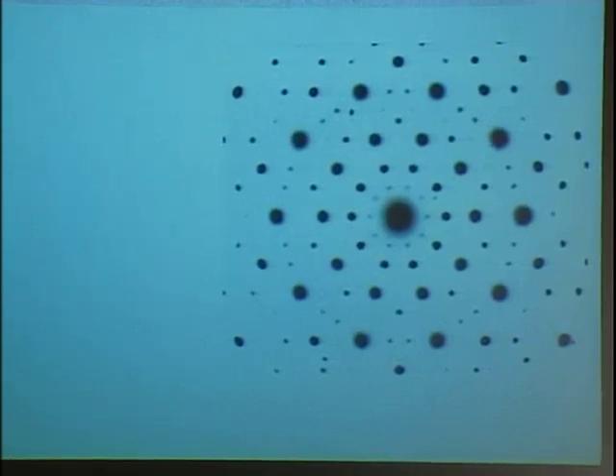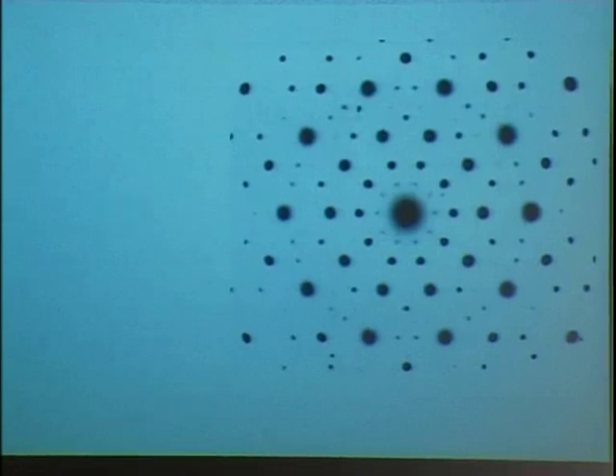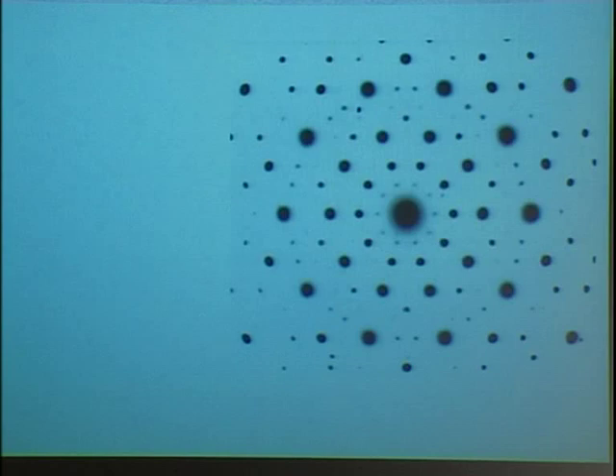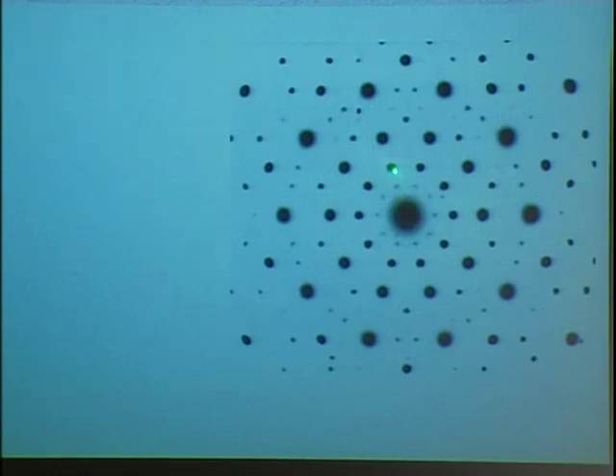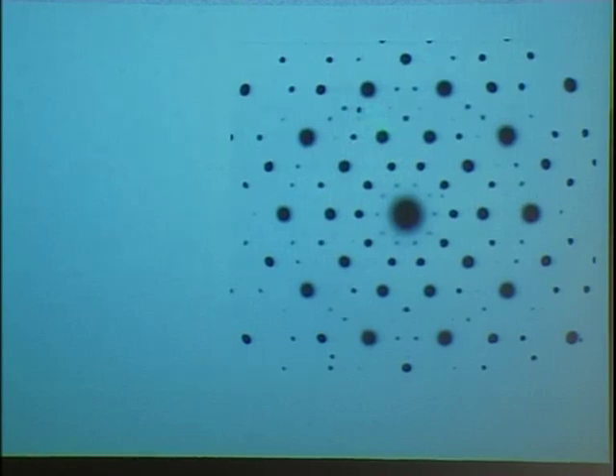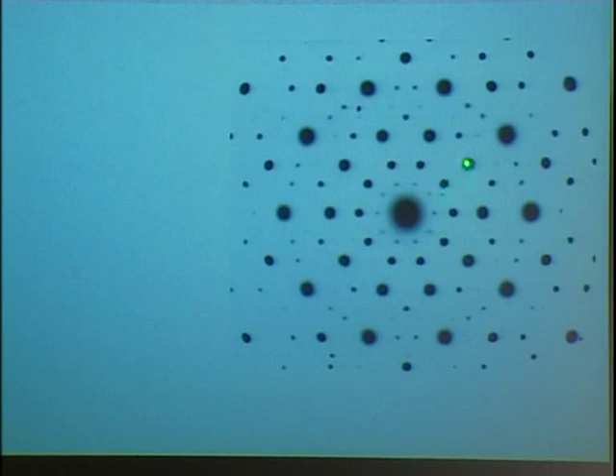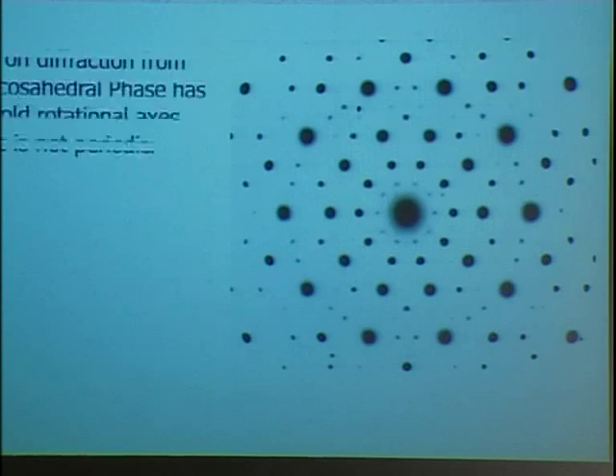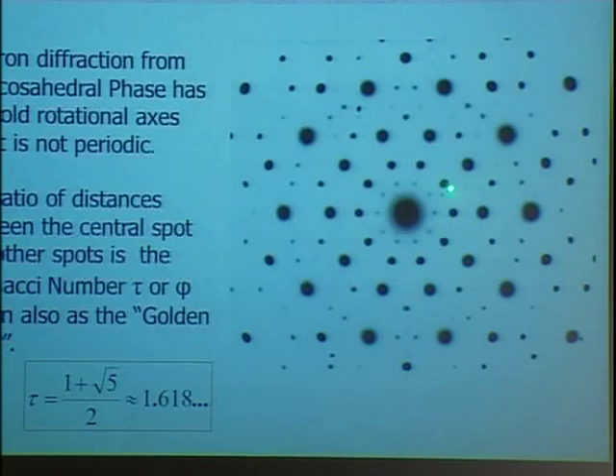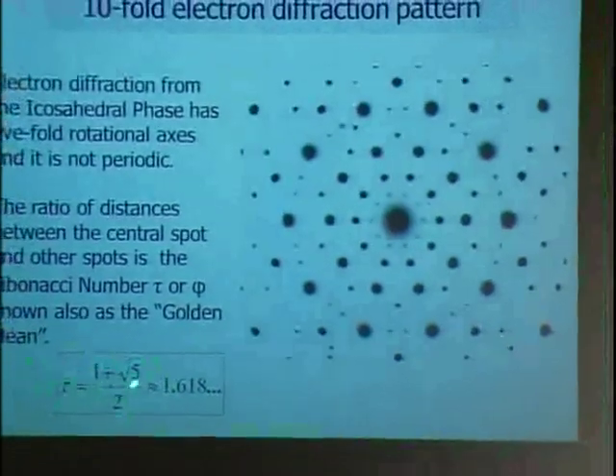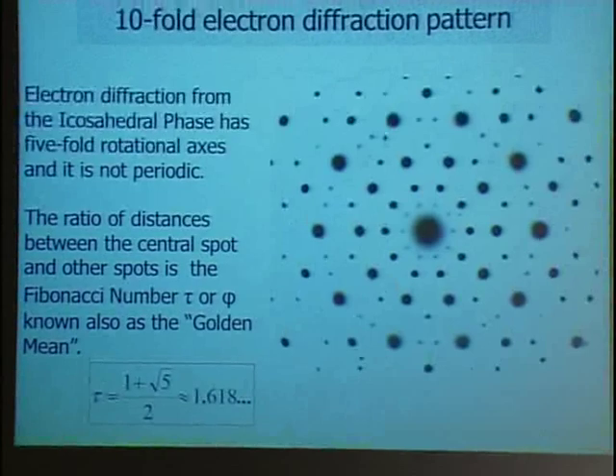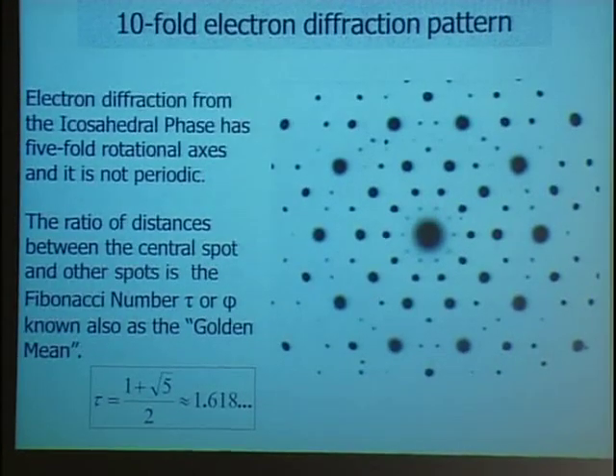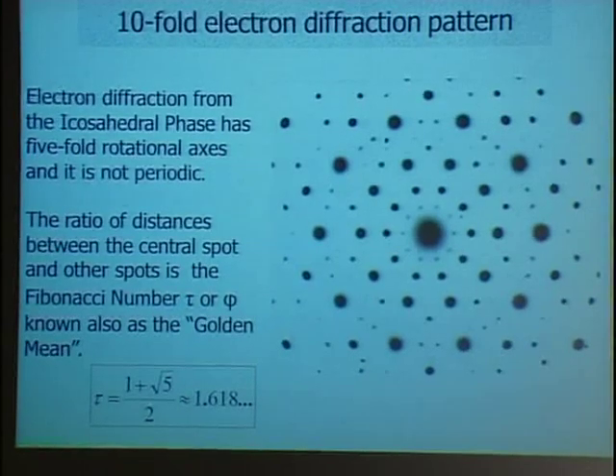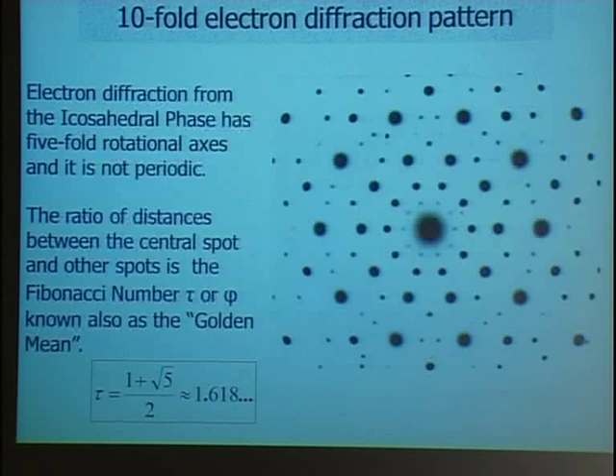But this is only one thing that is strange about the diffraction pattern. You see, in this diffraction pattern, the periodicity is lost. No periodicity. Look, if you go in this direction, you take the distance from here to here, you multiply it by any integer, say 2, you get here. And there is nothing there. No periodicity. Well, turns out that the ratio of distances from here to here divided by this is an irrational number. Of course, you cannot do it by measuring and dividing. This should come from theory. And so this is the Fibonacci number, this ratio, which is this number here, 1 plus root 5 divided by 2, which is an irrational number. So irrational numbers came into crystallography, and tenfold symmetry, and no periodicity, and everything is on one diffraction pattern.